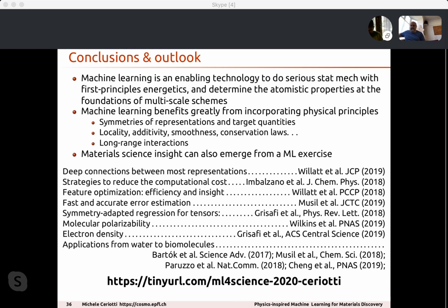Well, all of these can be very, very easily modified to predict forces and to learn from forces. People have been doing force matching for 50 years, and it's exactly the same thing. Your model predicts the energy, but it's a function of atomic coordinates. If you pick your representation right, it's a smooth function of the atomic coordinates, so you can differentiate your model, and then you can predict forces and you can train from forces. So there is no problem in using any of these models with molecular dynamics. And actually, using these models with molecular dynamics allows you to do a lot of smart tricks.